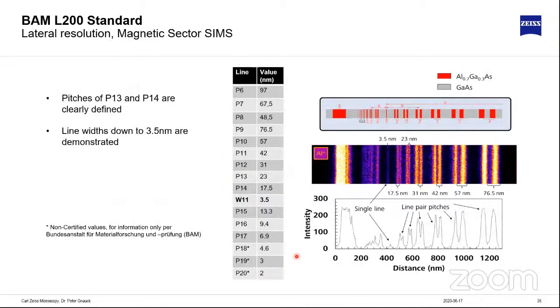And what is also very exciting is if we check the spatial resolution that we can achieve in an analytical mode, that's extremely high. So what we were using here, that's a standard sample that you can buy from the Bundesanstalt für Materialforschung. They generated a sample that consists of aluminum gallium arsenide and gallium arsenide, and it's a multi-layer sample, and it has line widths with a very defined distance. So we have a lot of double layers, double lines that we can look at.